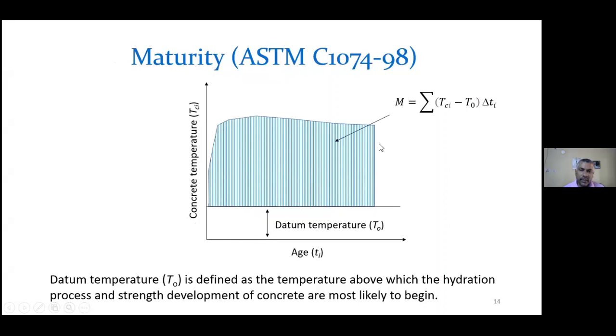So if we find out the maturity at this time, you should have the integration or the summation of this area, right? This shows the area under this curve. So at a particular time, the area up to that portion will give you the maturity. And this datum temperature is defined as the temperature above which the hydration process and strength development of concrete are most likely to begin. So therefore, if I keep measuring the temperature of the concrete, and if I know the datum temperature, I will know the maturity.